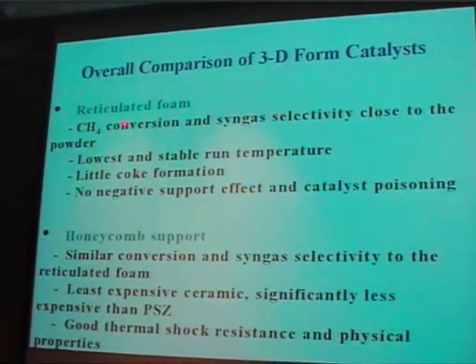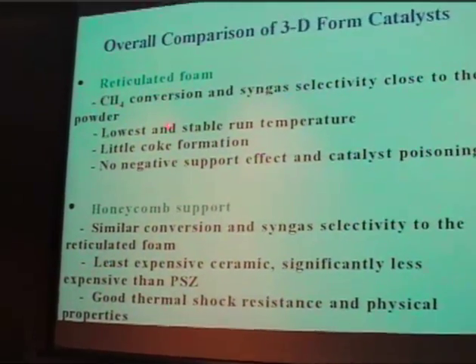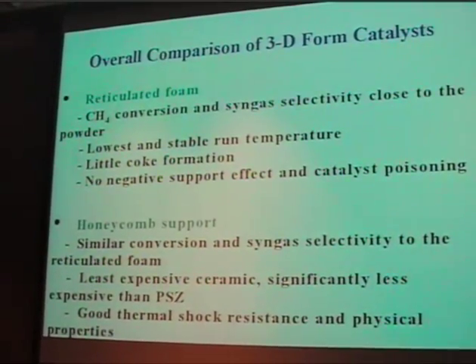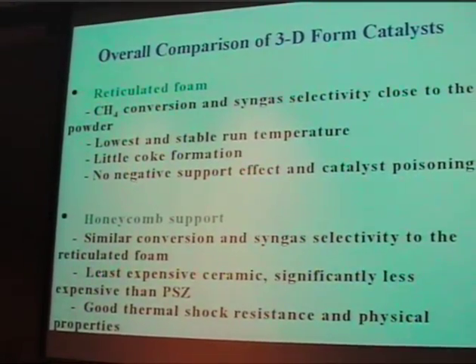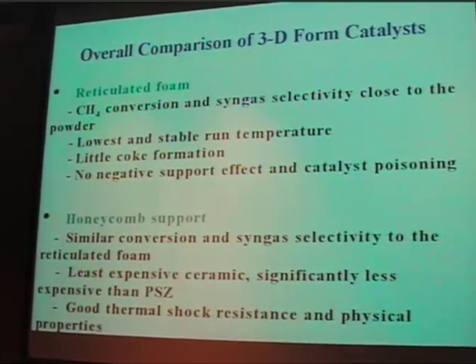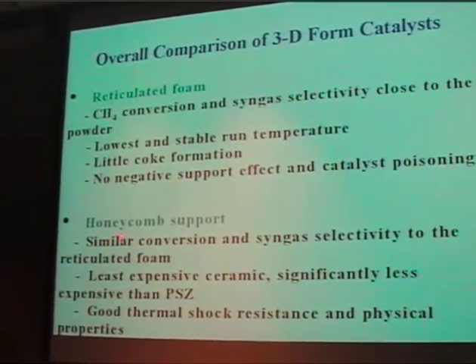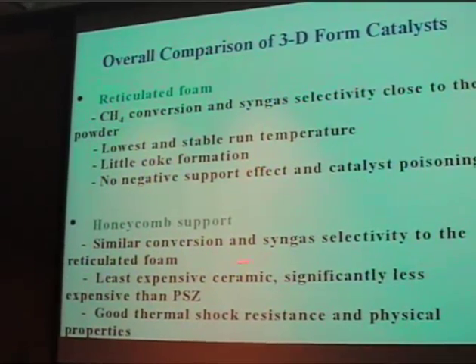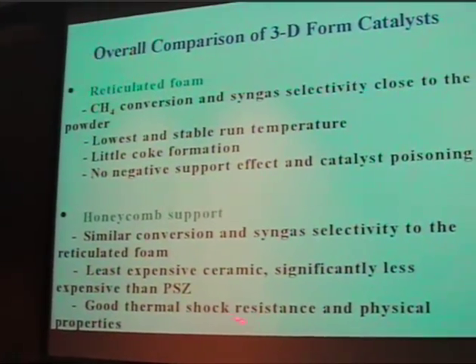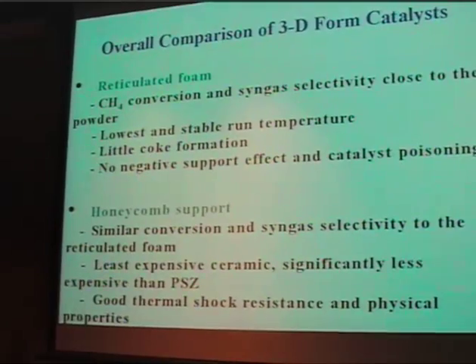All right, so overall comparison within the 3D structures. The reticulated foam, we like this one quite a bit. It had some of the lower run temperatures. It ignited lower, ran lower. We thought that would be good. Had very little coke. And then you don't have to worry about the support effect because the catalyst itself is the support. The honeycomb looked very attractive too, due to its low cost and also good thermal shock resistance. So we moved forward with those and what we called a very limited,